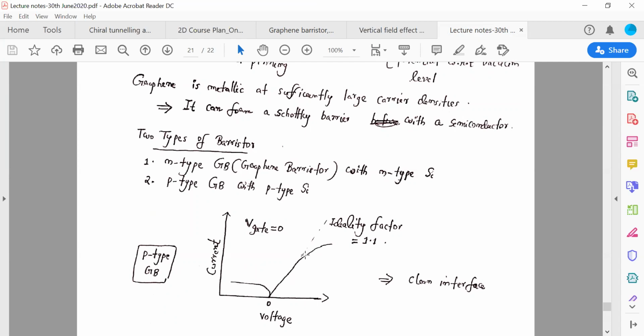So this actually tells you something. This is the low voltage region. This low voltage region gives you the junction resistance, the quality of the junction. If it is linear, then that is the best quality junction you have. So here when I say ideality factor 1.1, it's an indication that the interface between silicon and graphene is of the highest quality.